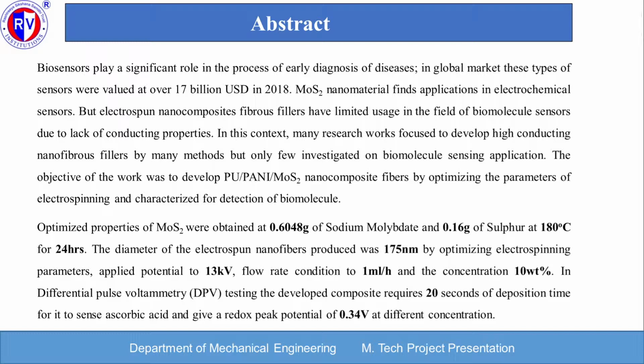Optimized properties of MoS2 were obtained at 0.6048 grams of sodium molybdate and 0.16 gram of sulfur at 180 degrees centigrade for 24 hours. The diameter of the electrospun nanofibers produced was 175 nanometers by optimizing electrospinning parameters: applied potential of 13 kilovolts, flow rate of 1 ml per hour, and concentration of 10 weight percentage. In differential pulse voltammetry, testing the developed composite requires 20 seconds of deposition time to sense ascorbic acid and gives a redox peak potential of 0.34 volt at different concentrations.